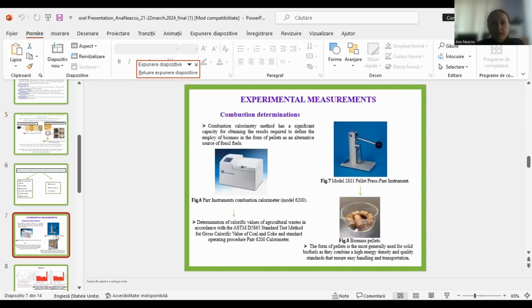The experimental measurements were performed using a combustion calorimeter in order to obtain the calorific values of the agricultural wastes. The samples were used in the form of pellets. We obtained the pellets using a manual pellet press. The form of pellets is the most generally used for solid biofuel, as they combine a high energy density and quality standards that ensure easy handling and transportation.